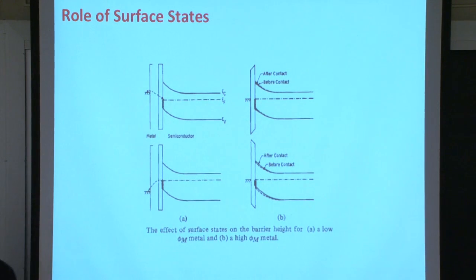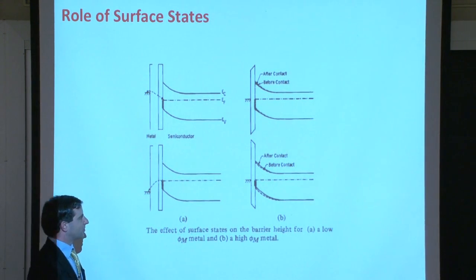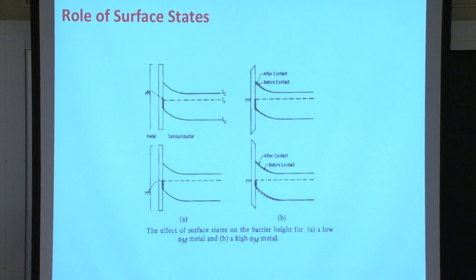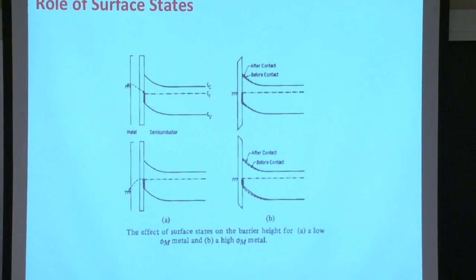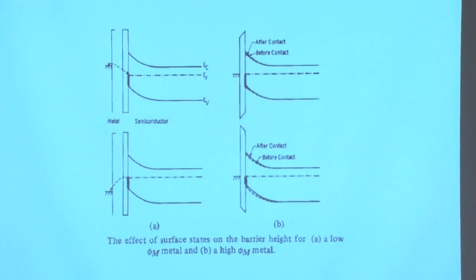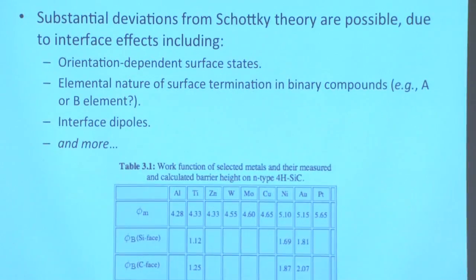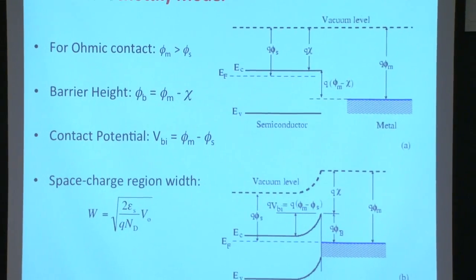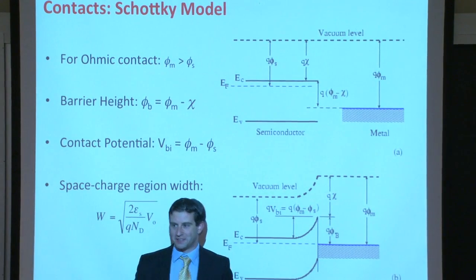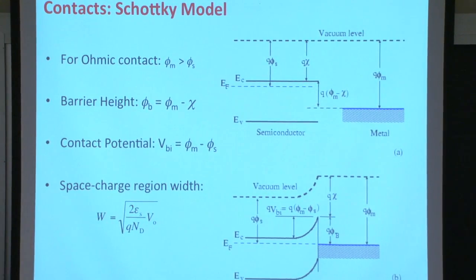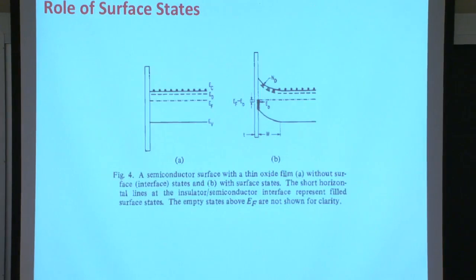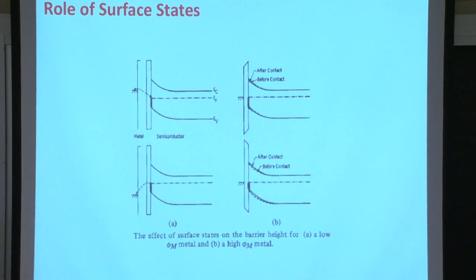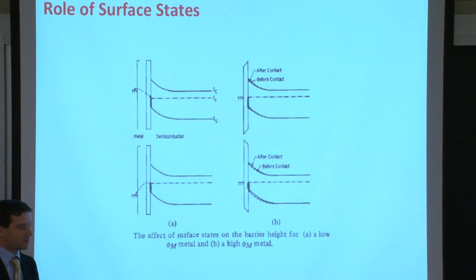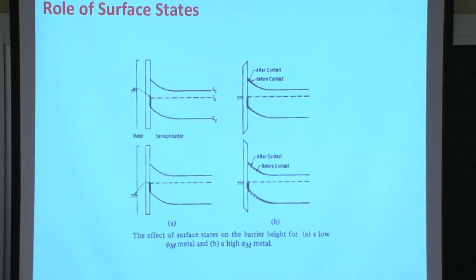And pretty much no matter what metal we deposit on top of our sample, we can wind up with a certain type of behavior of the semiconductor, a certain current voltage response. And this can drive someone absolutely insane when you're in the laboratory trying to get a repeatable contact and everything is changing all the time. And you walk through the math, and you know that you should be getting, let's say, an ohmic contact, you walk through the math and you derive the energy band diagram of the interface, and then you go to the lab and over and over again, you obtain a Schottky contact. And it just drives you insane.